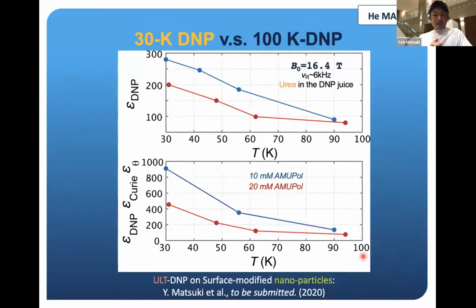Now, what about the enhancement factor? As we expected, it steeply went up with dropping sample temperature and reaching 300 at 30 Kelvin at 16.4 Tesla. For the total sensitivity gain, including the Curie factor as well as the depolarization effect, it's reaching a factor of 1,000. It's kind of impressive number, right? It's like 10 times better than conventional 100 Kelvin DNP.